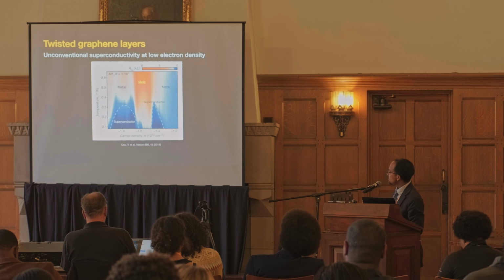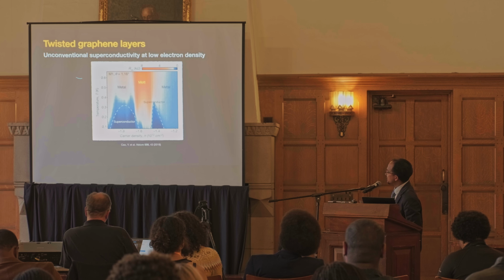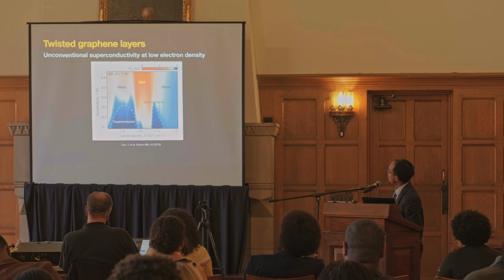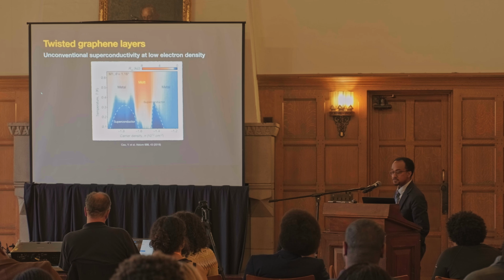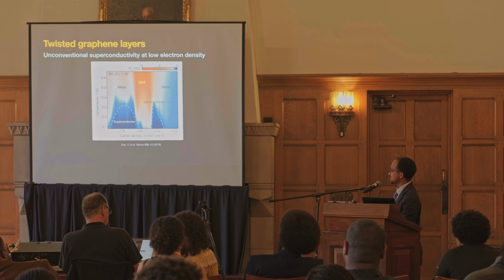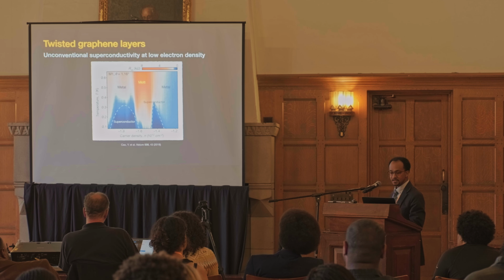And in 2018, a group at MIT discovered that when they created these twisted layers and cooled them down to really low temperatures, to be fair, they superconducted. But what was interesting was that the density needed to get the superconductivity to happen was extraordinarily low. You needed very, very few electrons for them to still interact extremely strongly, leading to superconductivity. This was an amazing discovery that really caused the field to go crazy and has launched an entire subfield in condensed matter physics.